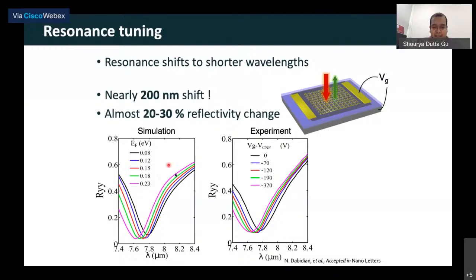Similarly in experiments, of course, we actually change the voltage, shown here between 0 and 320 volts. What we see is the resonance changes from 7.8 microns to around 7.6 microns. So what this is telling us is we can change the resonance and thereby choose which molecular absorption band this resonance overlaps with, and thereby enhance it. This allows us to reduce the multiple structures that we made, because our resonance was limited to one molecular feature, to a tunable structure that we can use for sensing different molecular absorption bands.